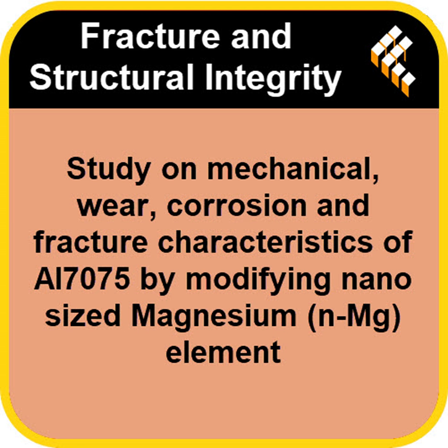And the material even helps itself out, doesn't it? It does. A neat little feature they observed was that the beta phase within the modified alloy functions as a kind of solid lubricant, which further reduces wear loss. However, the SEM analysis of the worn surfaces still showed clear scratch marks. This confirms that even with the added protection, abrasive wear, hard particles separating and scarring a surface, remained the primary way it was degrading.